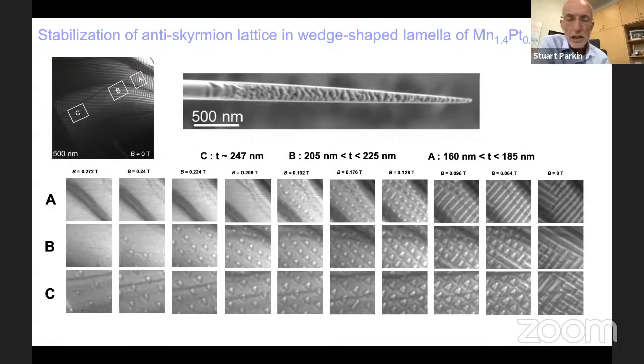This is work by Abe here in Max Planck. And you can see, if you look here on the left-hand side, black and white lines. Those black and white lines mean the ground state of this system under these conditions of magnetic field and temperature is no longer a uniform, perpendicularly magnetized layer, but rather it forms a helical structure where the magnetization rotates one-dimensionally from an up to a down direction in a sinusoidal fashion.